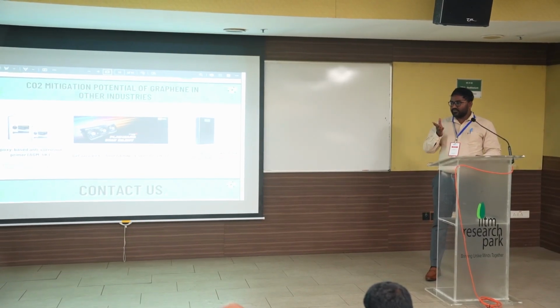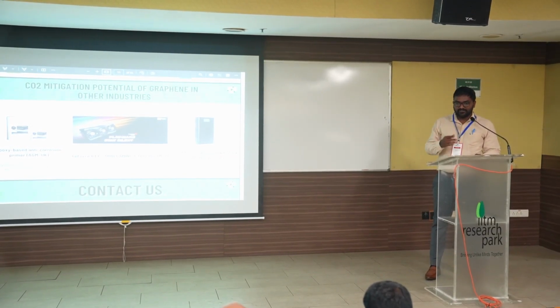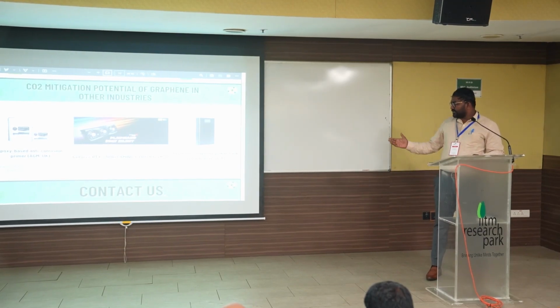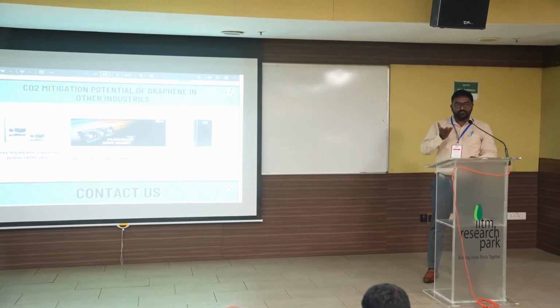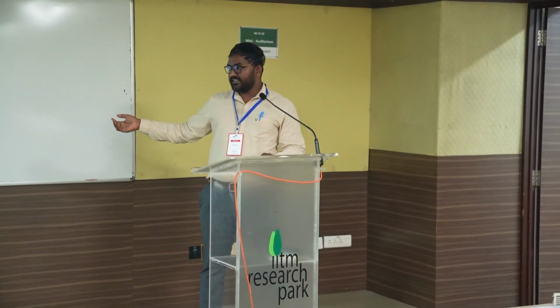The third example would be energy storage, which is something of very much relevance today. Flash Pro is a power bank developed by a company based in the USA. It has lithium-ion based chemistry, but the conventional lithium-ion based power banks usually have around 500 to 700 cycles, while using graphene in their cathode, they are able to improve their cycle life by 4 times. They have data which claims that this charger can go around 2,100 cycles.